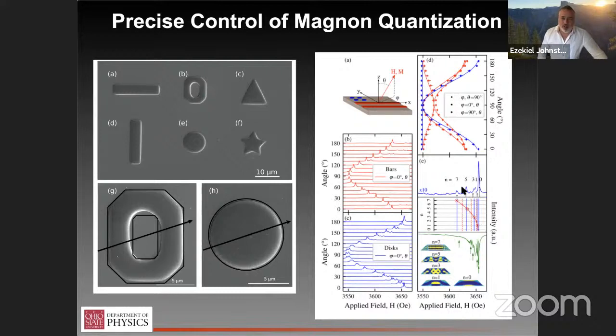So the first and the biggest impact in this context would be changing the quantization conditions. In terms of whether there's a thin film versus a thick film regime for the quality factor or the nature of the magnetic material, we don't really see any evidence of that, at least not yet. So it could be that there's some modest effect that's being swamped by sample to sample, just growth variations. But we don't see anything systematic in looking at the damping. And we have some cross-sectional TEM that does not show any variation through the thickness of the film beyond maybe a very thin interface layer.